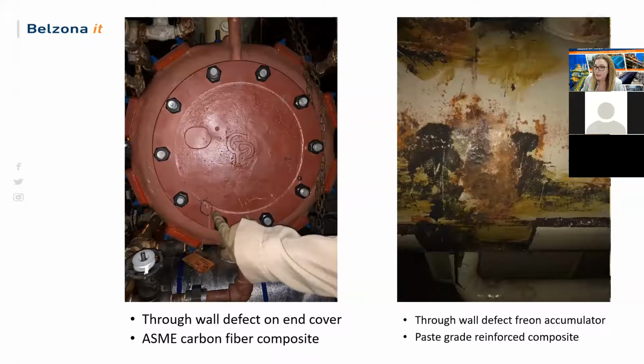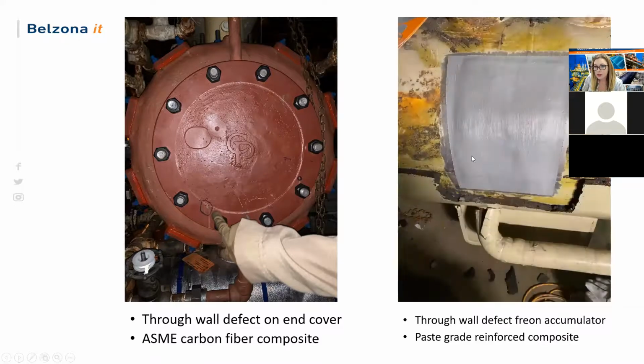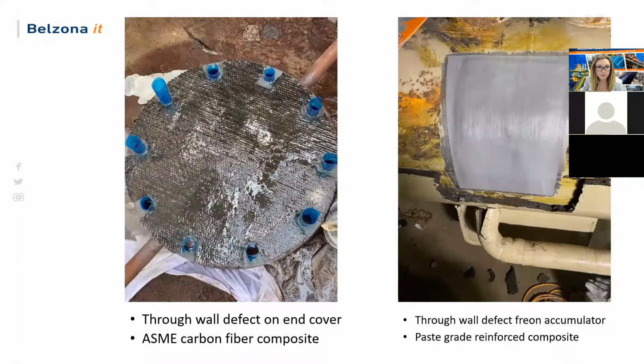This was also another emergency repair. They had a through wall defect on an end cover, as you can see here, and then on the shell as well in the picture on the right. So what we recommended was an ASME carbon fiber composite that we did on the internal of this cover. And then we did a composite patch on this one, which we went over with the ASME certified repair as well.